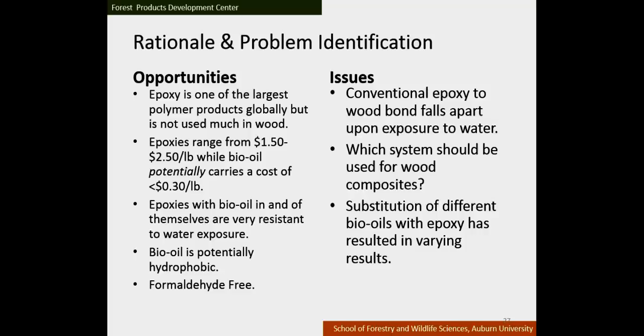But one of the issues, or several issues that we run into, is, like I said, the epoxy bond to wood will fall apart in water. There are different epoxy systems out there, but also when we look at different bio-oil, like if we take bio-oil through liquefaction and bio-oil through pyrolysis, the chemistries are very different, and so there are different reactions going on. On the surface it looks the same, but you get different epoxy to bio-oil ratios when you mix it together, whatever the optimal ratio is, the optimal recipe, if you will. And so getting something consistent is going to be important.